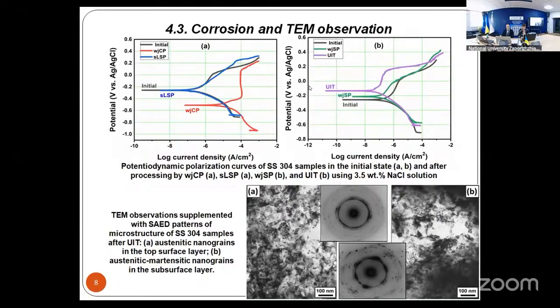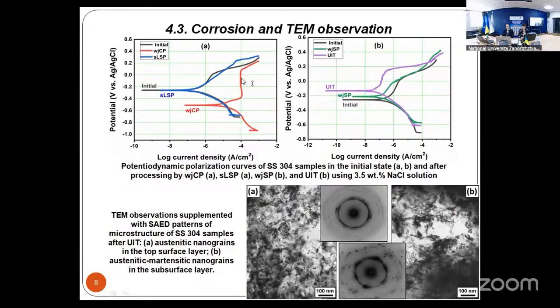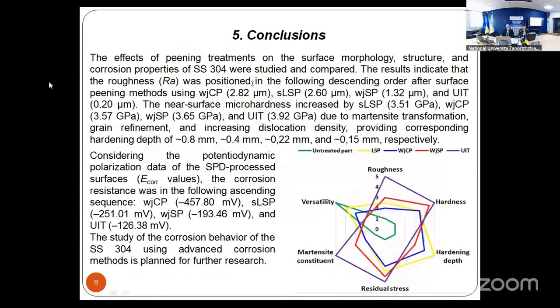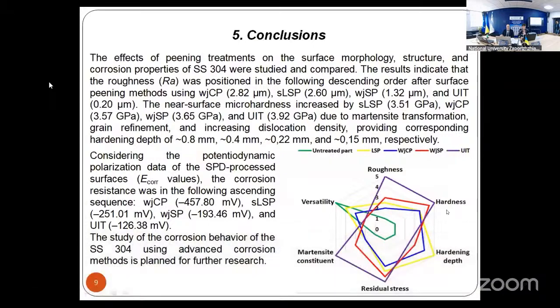However, the most indicative passivation region with almost constant passivation current was observed after cavitation treatment. The result indicates that the ultrasonic processing improves corrosion resistance more significantly by forming more favorable surface microrelief. The highest passivation ability was also found after cavitation and ultrasonic treatments due to single nanoscale austenite formed in the top surface layer. Considering the surface microhardness, hardening depth, residual macro stresses, nanostructuring effect, and structural roughness parameters obtained,